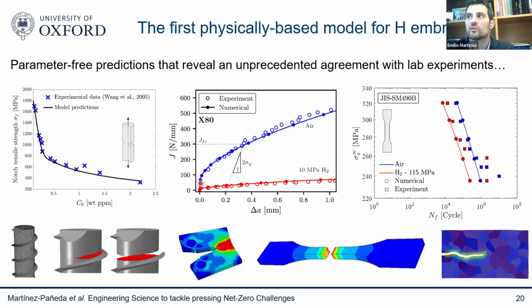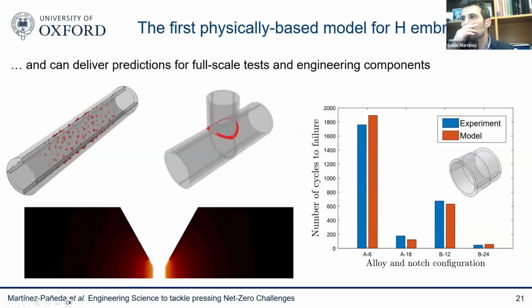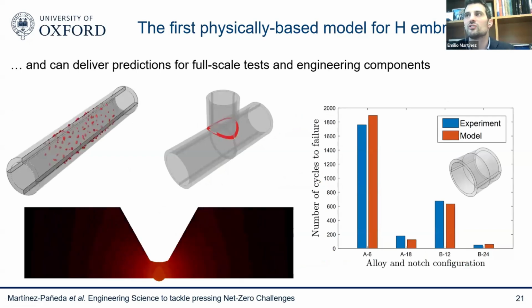These are called R-curves, crack growth resistance curves. And you can see that the model behaves very well in the absence of hydrogen. Then we expose that pipeline to a 10 megapascal hydrogen pressure, a typical value that is being considered, and we get, again, a very good agreement. This is fatigue cyclic loading. And you can also deal with the microstructure. You can deal with lab samples, and you can scale things up. You can also simulate with these models real complex engineering problems.